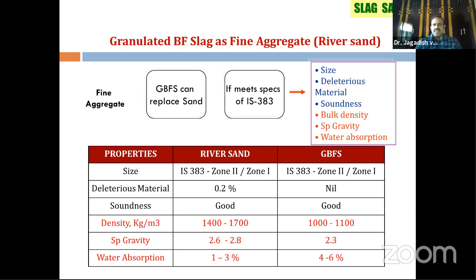And water absorption varies. But when they tested granulated blast furnace slag, if you wanted to use it as a river sand, it has to meet all these requirements. But when they check, density is between 1000 to 1100 kg per cubic meter. So what is the water density? 1000 kg per cubic meter. So if you have to use it, it should match with the river sand properties.